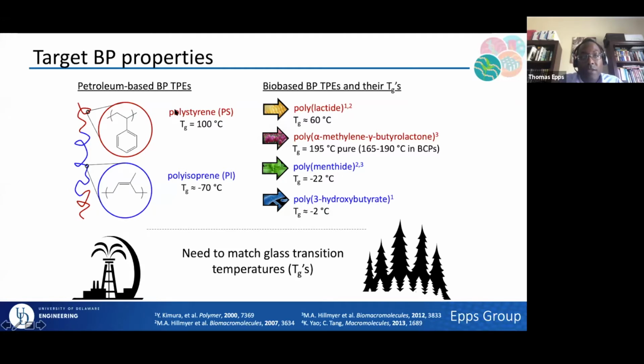However, if we're thinking about polystyrene replacements, you can see that polylactide in particular falls short when I start thinking about glass transition temperatures or use temperatures of these materials. I can also switch to something like a poly alpha-methylene gamma-butyrolactone type polymer. That's again quite nice, and in this case I get a glass transition temperature, which I can think of as a use temperature, of about 195 degrees. That sounds quite promising, but it also means I have to heat this material up to well above 200 degrees in order to thermally process it, which is very energy intensive.